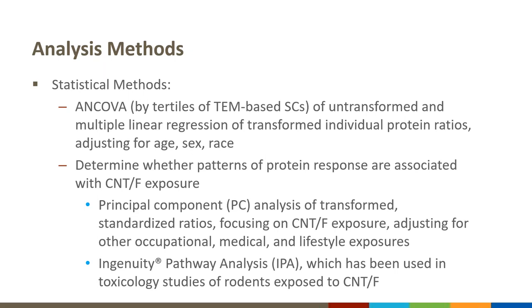exposure measure that we had in that it could detect very fine differences across the workers, whereas many of the respirable and inhalable elemental carbon measurements were below the limit of detection or were below the background level. So structure counts was the most sensitive measure of exposure we felt. So we emphasized this for this analysis. So we divided these across the group into tertiles, into three equally spaced groups based on the structure count concentration. And we used ANCOVA on the untransformed metrics.